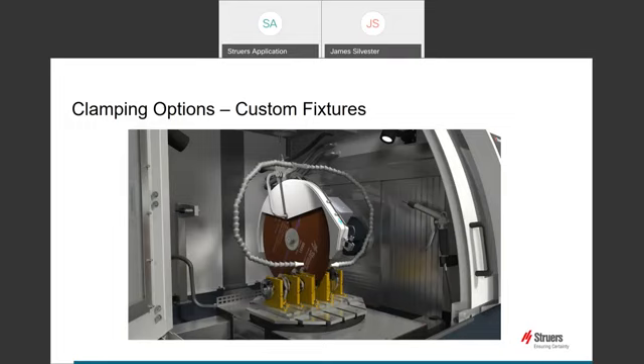The rotating bed was used to allow each end to be sampled, whereas a standard X table may not have the required travel to reach all locations. In addition to this custom clamp and rotating bed providing a solution for a complex shape, the use of intelligent measuring can ensure the cutting wheel travels far enough to cut the sample, even taking wheel wear into account and optimizing the wheel RPM to provide the best available cutting conditions.